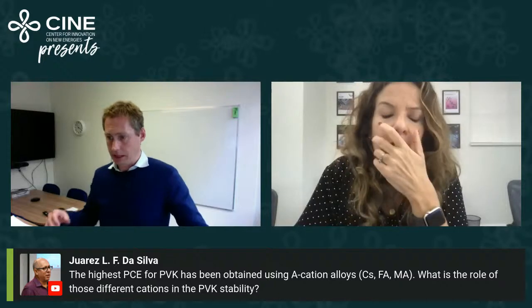Yeah, it's a very good question. So yes, the highest performances are certainly involving these alloyed systems. They're formamidinium rich, but they also have these other cesium and methylammonium cations as well. What we're seeing from this tilt work is that the cesium, the MA, these other cations, they're inducing some tilt in the octahedra. That's making them tetragonal. And what that does is it stops that phase from converting further to these hexagonal polytype phases, which are instability points in the cell.